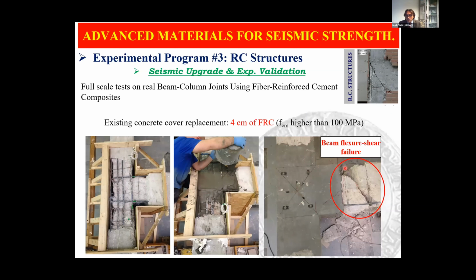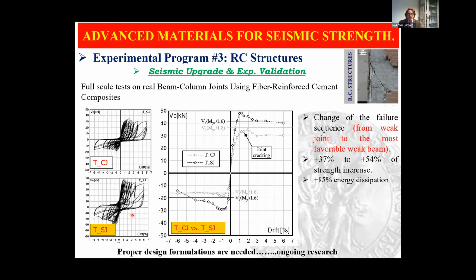And if we compare the performance of the control specimen with the strengthened one, and here you can see the envelopes, you can clearly understand that there was a good strength increase in the range of 37 up to 54%, looking at positive or negative performance. And then the increase in terms of energy dissipation capacity was about 85%. Obviously, this is a new solution. Proper design formulations are needed, but it's a good opportunity, especially when concrete is very poor.